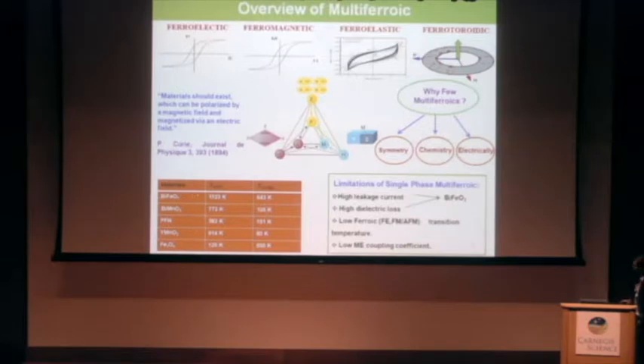Among all, only bismuth ferrite is known as a room temperature multiferroic material, but it is not applicable for practical devices due to its high leakage current and high dielectric loss. And the other multiferroic materials have either the ferroelectric or ferromagnetic transition below room temperature. So due to this large disparity between the ferroelectric transition temperature and ferromagnetic transition temperature, the magnetoelectric coupling is very small. So in order to achieve strong magnetoelectric coupling above room temperature,